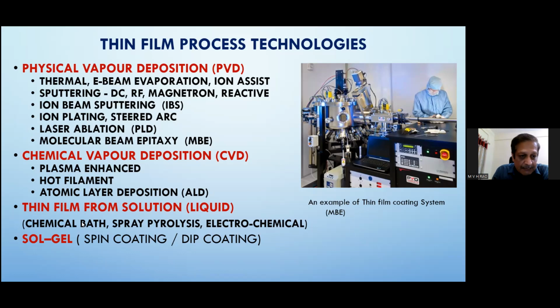Okay, chemical bath deposition. These are all much simpler, easier techniques. Suppose a supersaturated solution is there. We all know that with a supersaturated salt solution, if you put a salt particle in it, it will immediately crystallize the whole solution. In a somewhat similar way, we dip a substrate in a supersaturated solution of certain material like cadmium sulfide selenide or zinc sulfide selenide. Once they find certain nucleation centers on top of the glass substrate, some nuclei slowly form because of the supersaturation, the condensation.